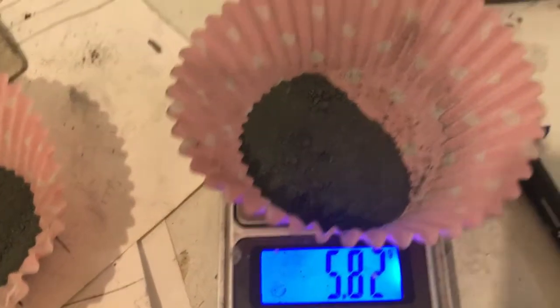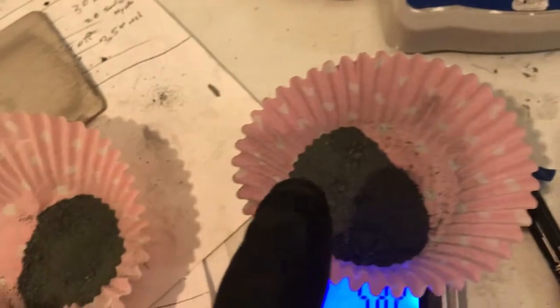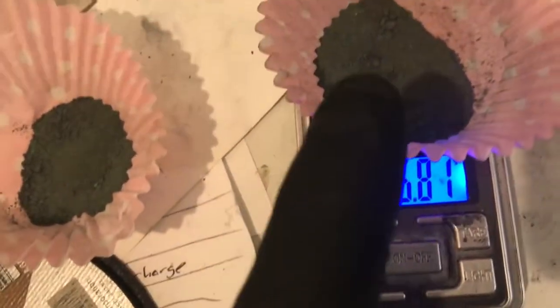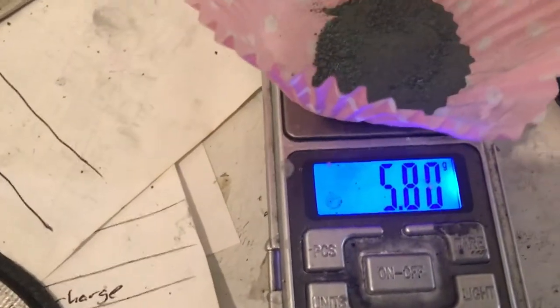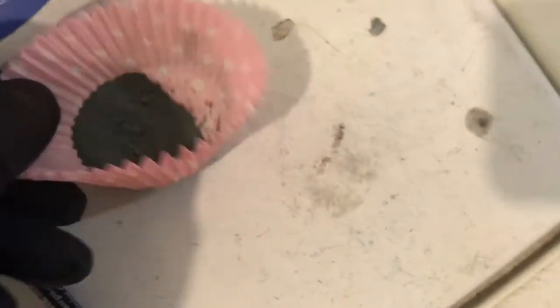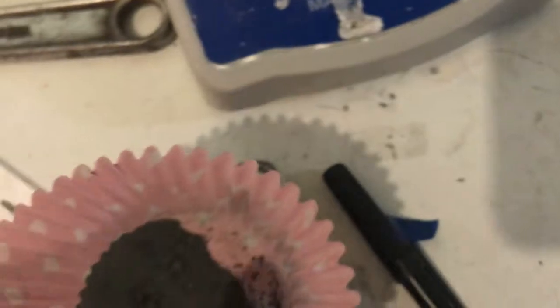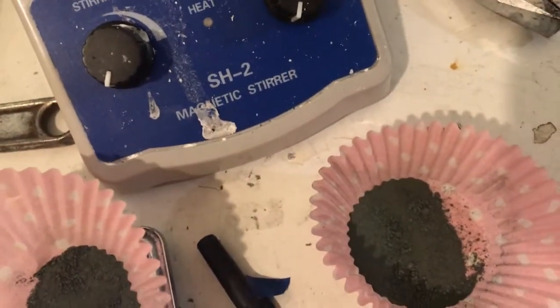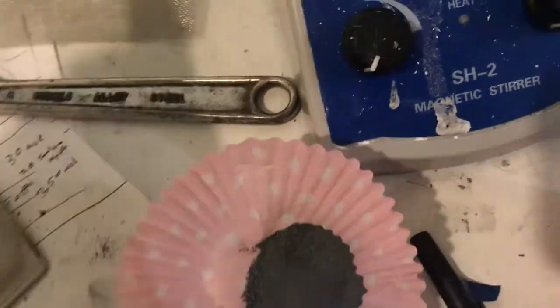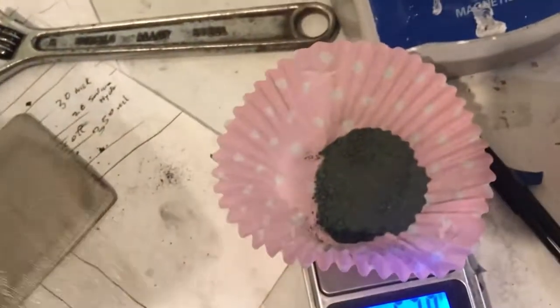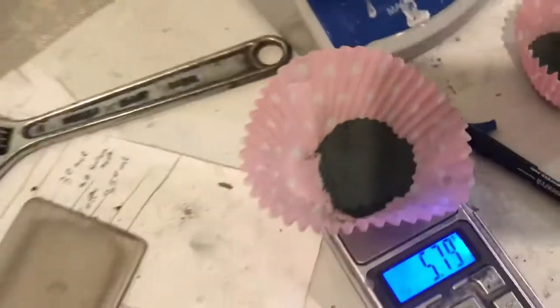Okay, weighing up the active material, the nickel hydroxide mixed with some carbon which fell off of the dipping process. So we have 5.8 grams on one side and 5.79 grams on the other side. I'm getting ready to paint one side and sprinkle this stuff. It's going to be put on this screen and sprinkled over the conductive ink I'm going to coat over this.